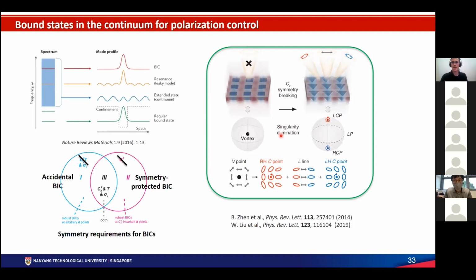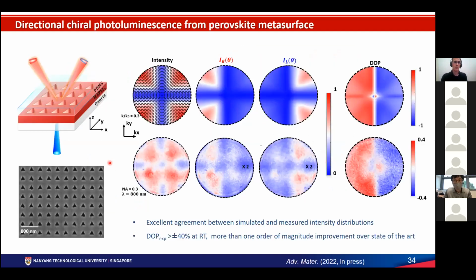In order to see how the polarization spans the entire Poincare sphere, we take back focal plane imaging. We also do simulations to see what kind of polarization you would expect. You see a 4-lobed intensity in the simulation, which is shown very well also in experiment. On the left half of the hemisphere you will see mainly right-handed polarization, and on the right half you will see mostly left-handed emitted light. If you measure the degree of optical polarization, theoretically you can obtain fully circularly polarized light.